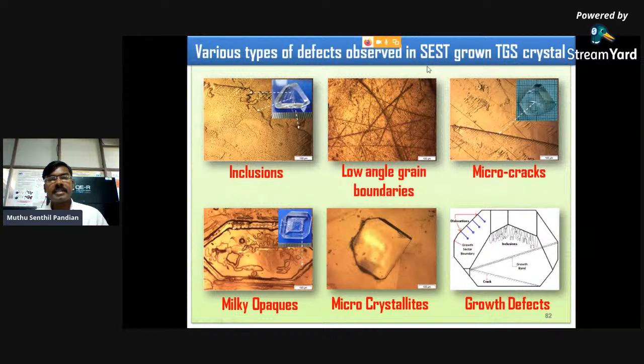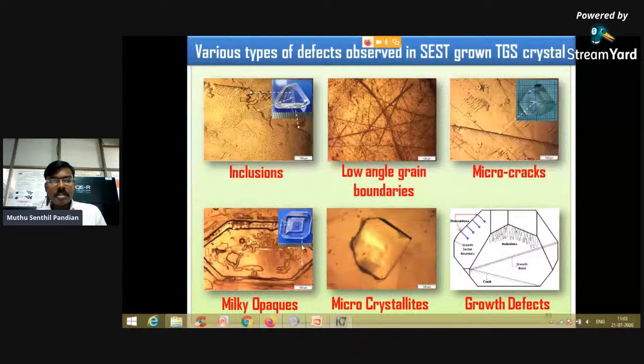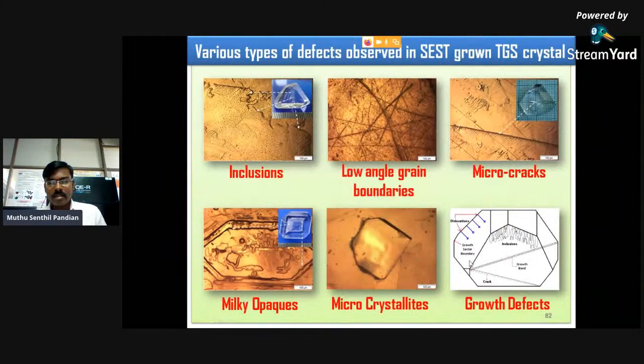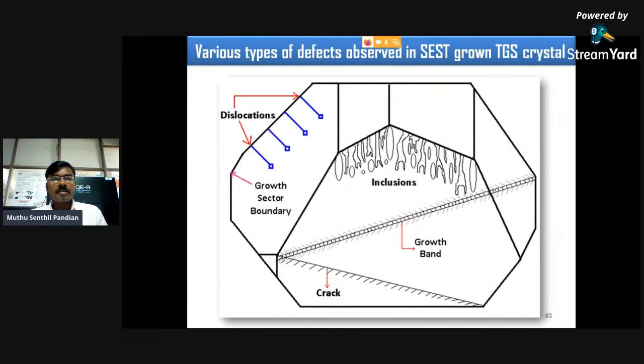So these are various types of defects appeared in the conventional method grown TGS crystal. There are solvent inclusions due to the temperature instability. There are low angle grain boundaries we have seen in the HRXRD measurements. Micro cracks, which we can visibly see in any conventional method grown crystals. Milky opaque regions and microcrystallites. These are some of the growth defects that appeared in almost all the conventional method grown crystals because of the temperature instability and the availability of the material ingredients. Almost all the conventional method crystals have this kind of inclusions, grain boundaries, microcracks, milky opaque regions, and microcrystallites.